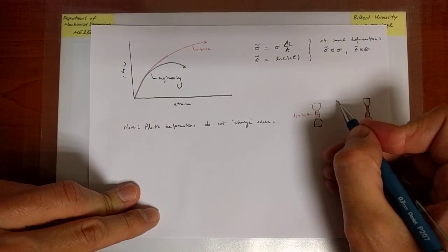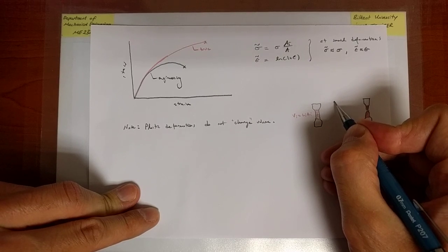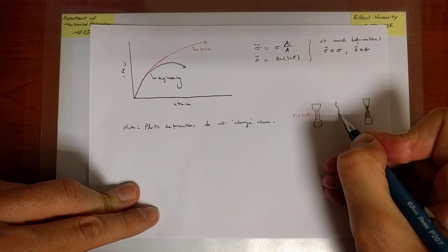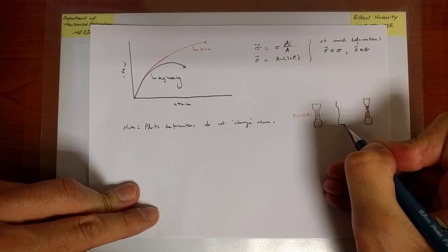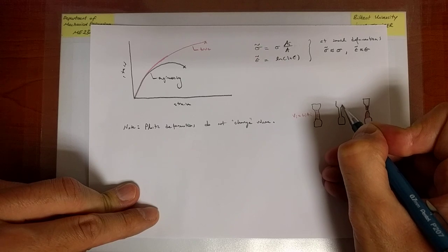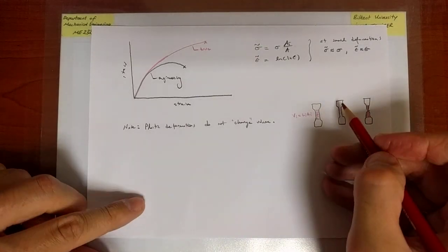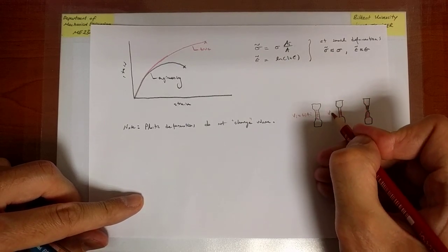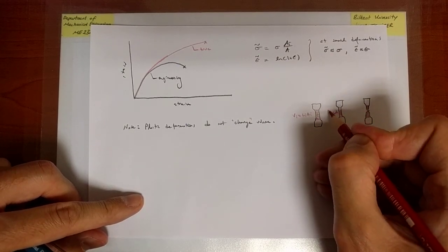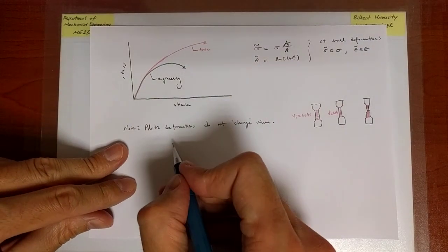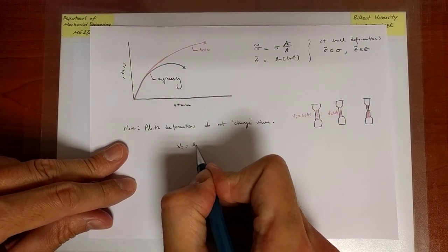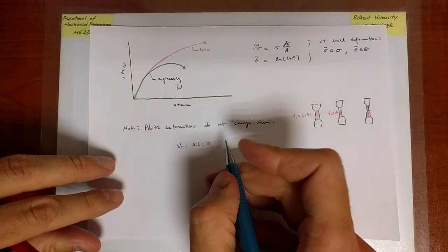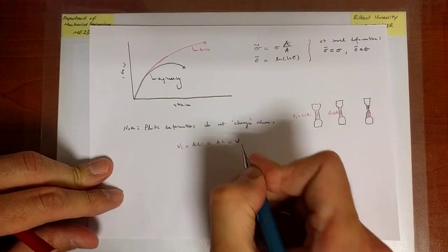And therefore, if I look at the portion of the curve at some earlier stage before the specimen breaks, and I'm going to look at a region before necking occurs. So the specimen is slightly longer now, it's slightly thinner, and the current length times the current area is the current volume. So what we are saying here is that the initial volume, which is A_i L_i, is for all practical purposes equal to the final volume, which is A times L.